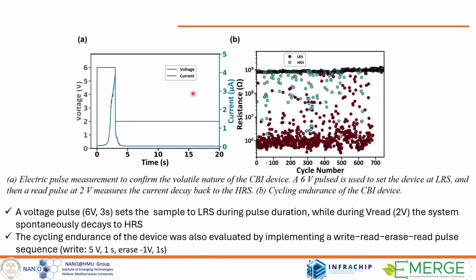Then we send some pulses with extended duration. This was a 3-second pulse, and then we monitor the current. We observe a firing process at the end of the pulse. But then when we remove the pulse, the system very quickly drops to the high resistance state. So it was a quick diffusion back to the high resistance state.